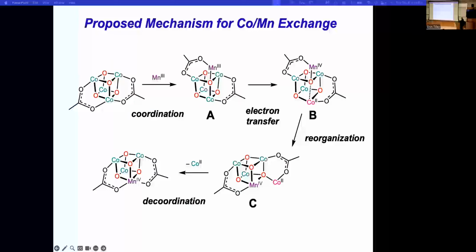We're quite convinced that the cube binds the incoming metal as a Lewis acid like this. And then there's an electron transfer that converts one cobalt 3 to a cobalt 2. That weakens the linkage of that cobalt in the core of the cube to an oxygen. And the manganese 4 that's produced now fits in perfectly. And so it swings down as the cobalt 2 swings out. There's that reorganization. We come by decoordination to the final product.